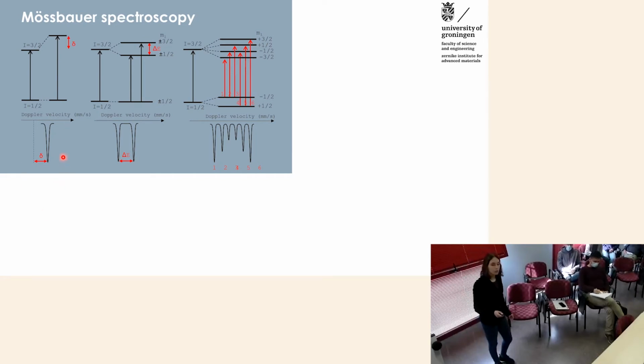The way it works is that the nucleus absorbs the radiation, and when the atom is free without any chemical environment, we will only observe one peak, at the horizontal shift which is characteristic of this atom. But when the atom, in this case iron, is in some kind of chemical environment, the peak will be shifted. First, it will have a shift which corresponds to its oxidation state. And then it's possible that it also has splitting due to its chemical environment.